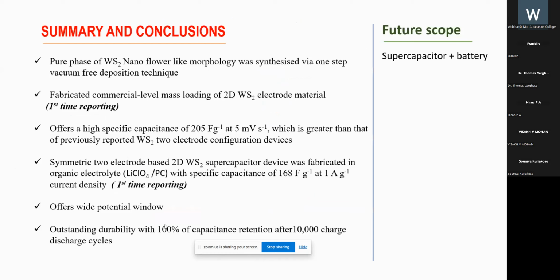It offers a high specific capacitance of 205 farad per gram at 5 millivolt per second, which is greater than previously reported WS2-based devices. And also in organic electrolytes, we have reached 168 farad per gram at 1 ampere per gram current density, which is also first time reporting. Both devices show 100% stability over a large number of cycles, that is 10,000 charge-discharge cycles.